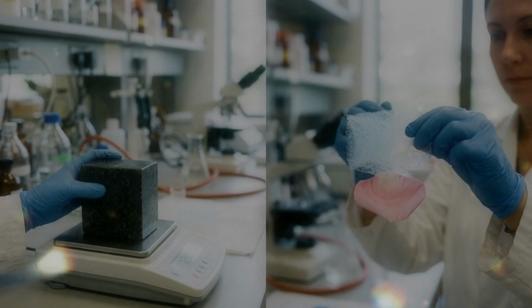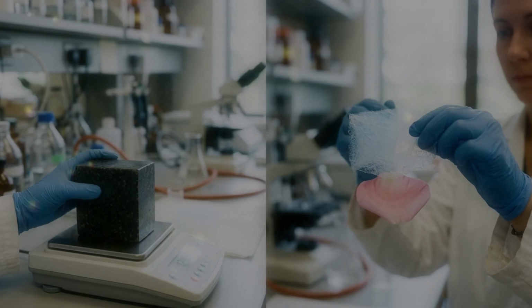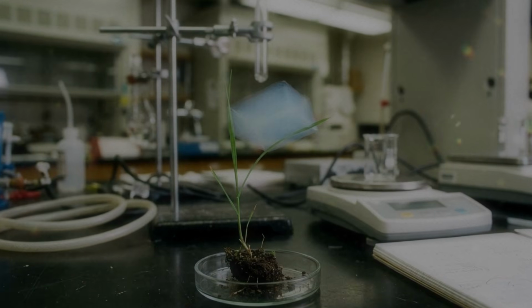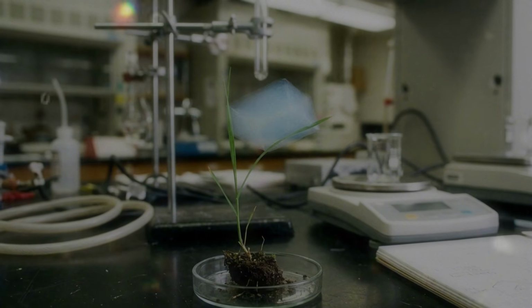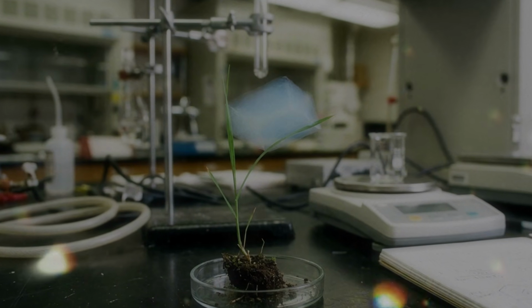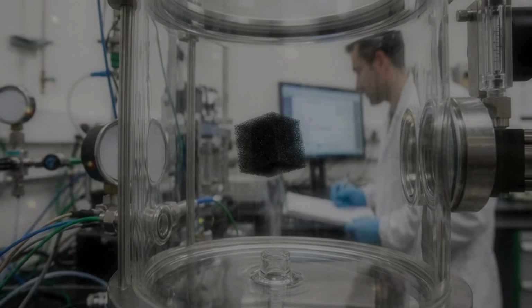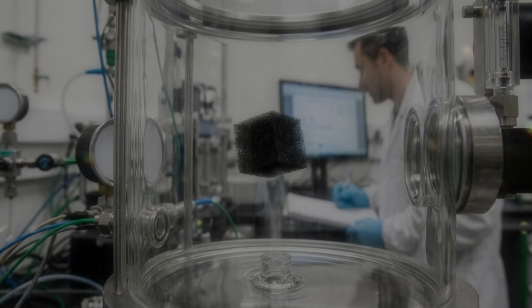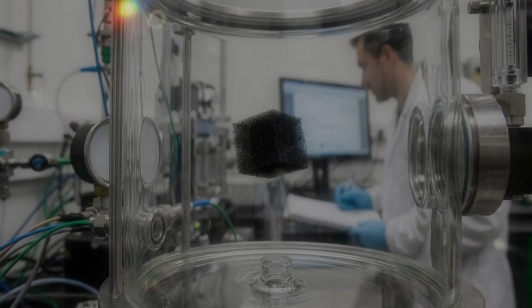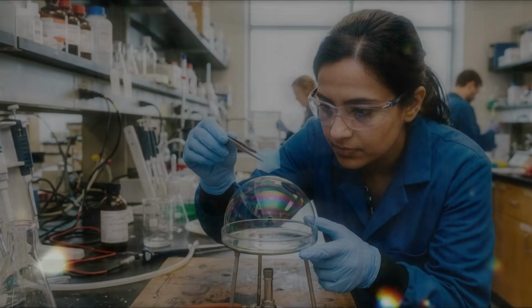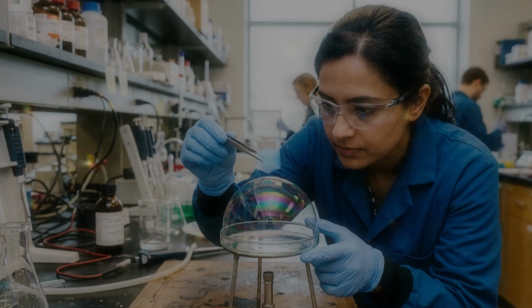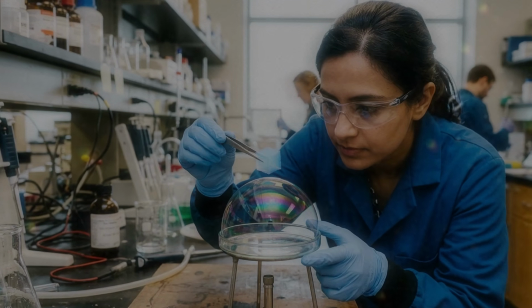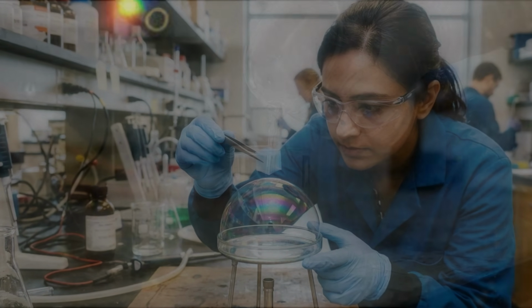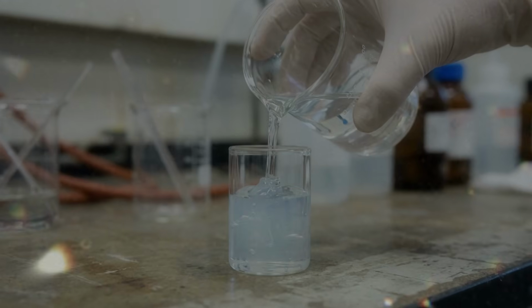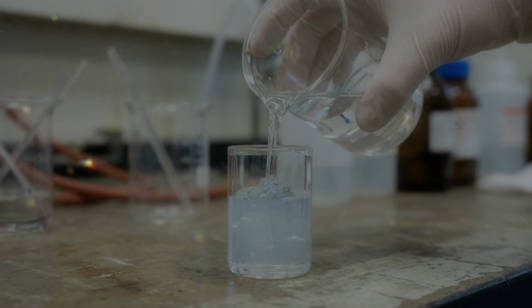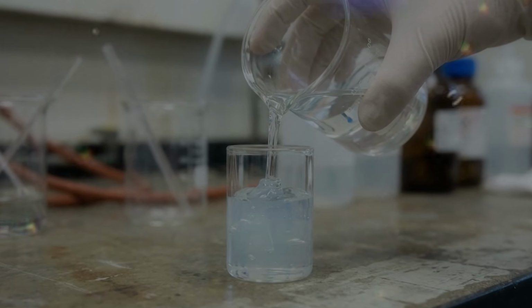Cellulose-based aerogels and flexible transparent films are receiving particular attention. Cellulose is widely available from plants, and carefully processed fibers can form light porous structures with good optical and thermal behavior. Large clear panels are difficult because a small difference in density can scatter light. Cracks are easy to see, and moisture can alter the structure. Attaching the aerogel to glass without creating bubbles or cloudy regions requires careful processing.